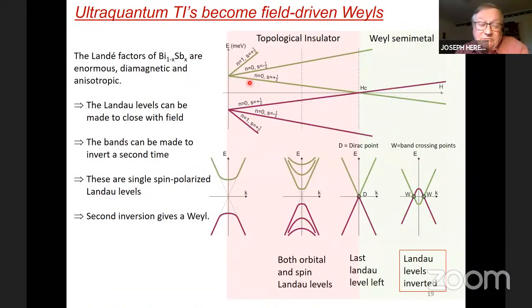So if I look here at the magnetic field dependence of the band structure, you have conduction band edge and valence band edge at the L point here. They split into Landau levels, but the last Landau level, orbital quantum number 0, spin 1/2, closes. And it closes at this critical field H sub C, where you have a genuine Dirac point, and beyond which the bands cross again. But now that they cross, they form Weyl points. So Nandini's student calculated the chiralities and integrated the chiralities over these two points, and the integrals flip from plus one to minus one. So these are genuine Weyl points as calculated.